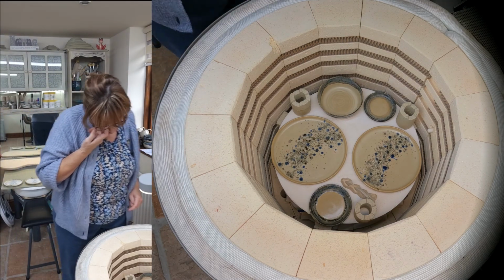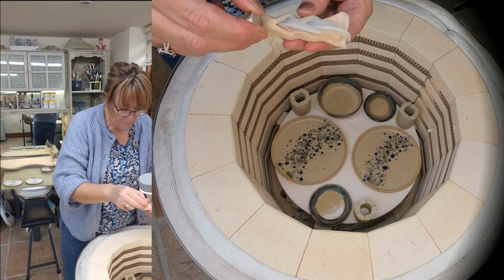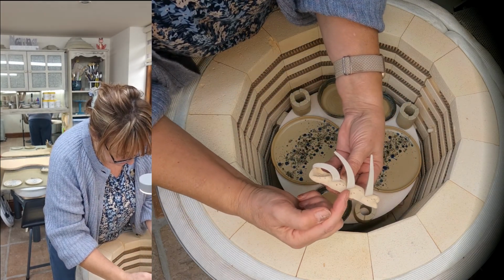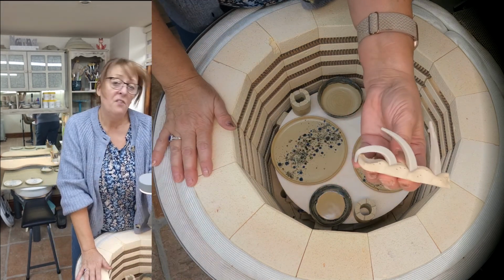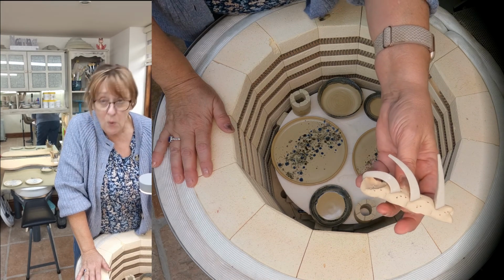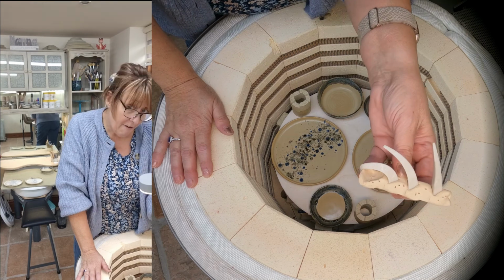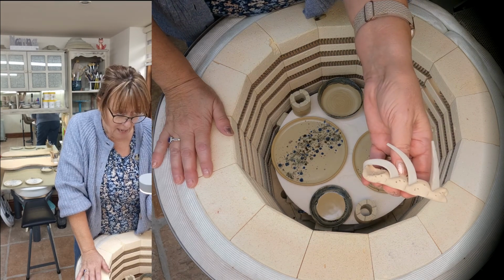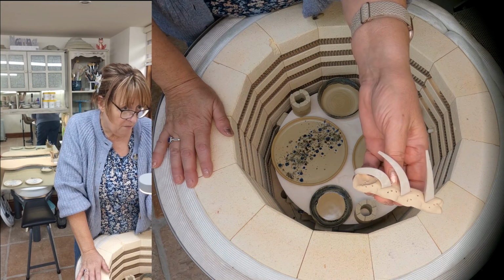Oh, okay. So I was aiming at a 5.5. This is 5. This is 6. This is 7. With my limited knowledge when it comes to kilns, I think that's way more than a 5 because it's gone completely over. 6 hasn't come down. So I reckon I've hit a 5.5 there, which is what I'm aiming for with the Mako, which are cone 5, cone 6.